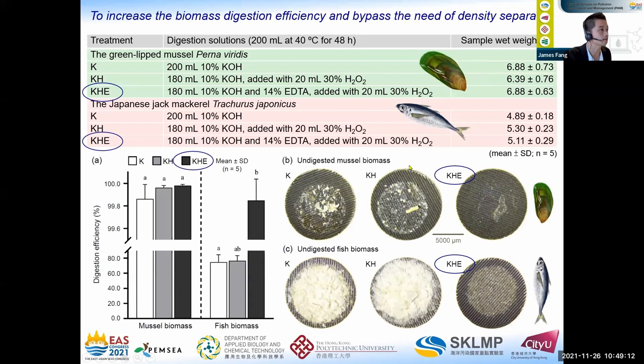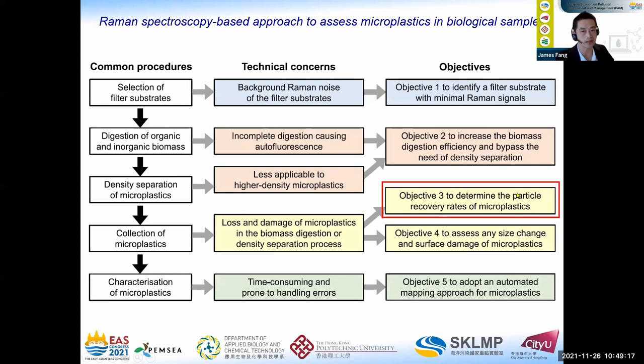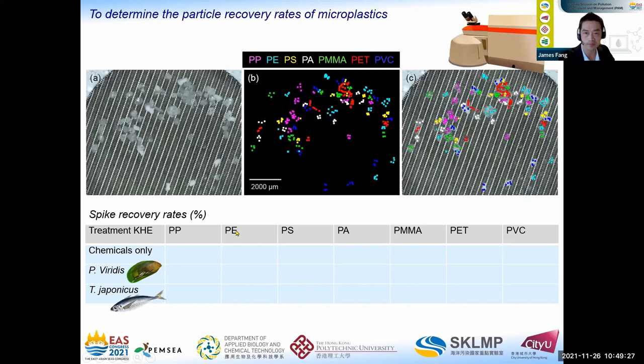What's next? The next objective is to determine the particle recovery rate using the KHE treatment. What do we do here? We have three treatments: KHE chemicals only, the KHE solution with the mussel biomass, and with the fish biomass. We use seven types of microplastic in this evaluation. We mix all this plastic together and split into the three treatments, which were subject to the same digestion procedure. After the digestion, we retrieve this plastic particle on stainless steel membrane